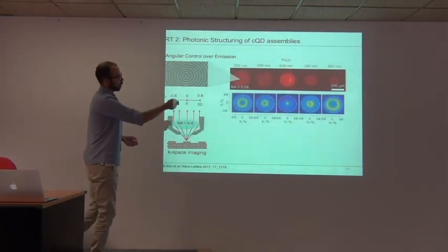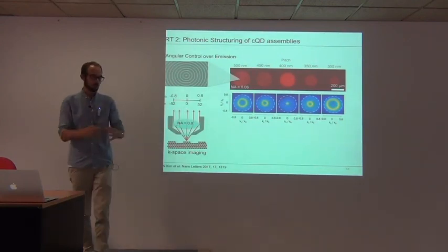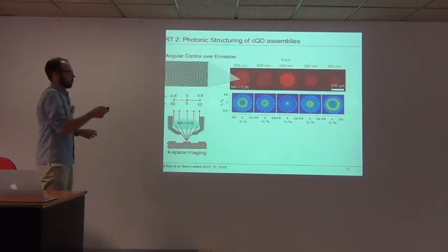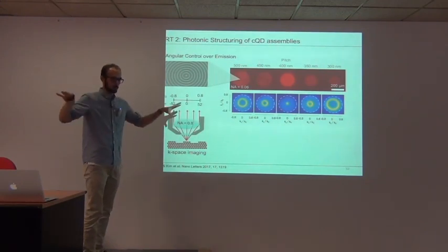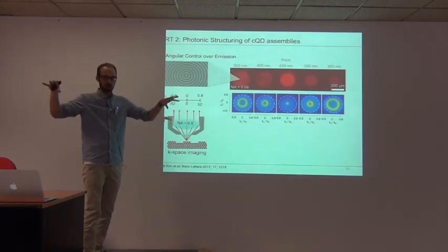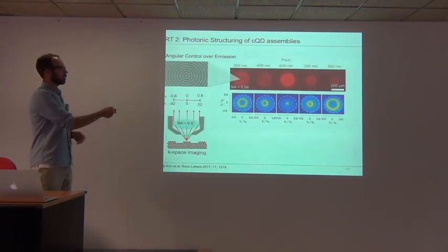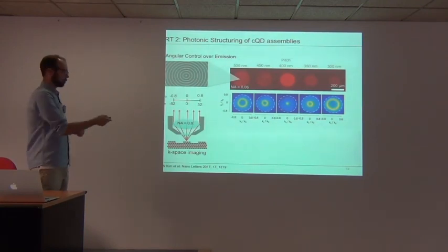And indeed, for the 400 nanometer case, we get this high intensity at the center, meaning that this is really a beam of fluorescence that is now coming off of the sample. And again, what is important to remember is that this is nothing else than just taking the quantum dot film and creating a little bit of structure in the ensemble. You're promoting the outcoupling of light very nicely. For other pitches, you are emitting at a higher angle, so this creates these kind of donut-shaped beams.